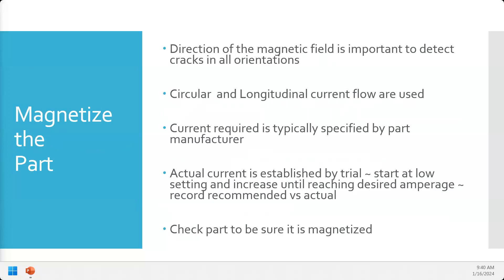Our testing devices have the ability to magnetize in both directions. For portable equipment, we attach the electromagnet one direction, do the inspection, then turn it the other direction and repeat. The current required is typically specified by the part manufacturer and is related to the size of the part — bigger parts need higher current to reach saturation, while smaller parts shouldn't be overheated. Actual current often has to be established by trial, starting at a lower amperage and increasing.